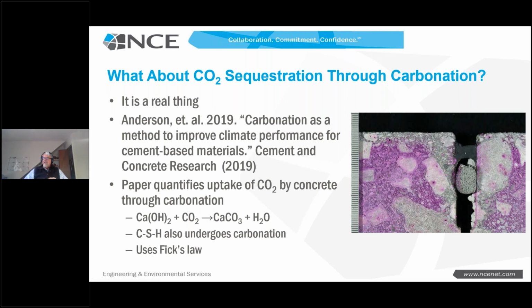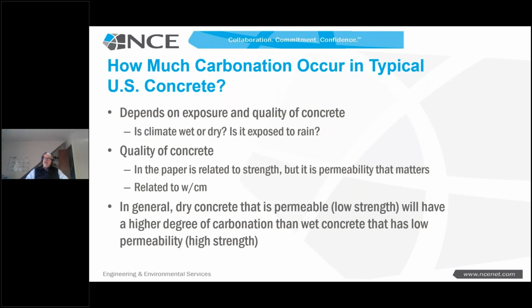And so this paper by Anderson et al., it's a great paper. It does talk about how CO2 uptake occurs, how we're converting the calcium hydroxide and CO2 to calcium carbonate, and it uses Fick's law, the assumption in the paper, and depends on the exposure and quality of concrete. And so if you are in a dry environment or an area that has periods of a lot of dryness, so maybe between monsoons, for example, and you have concrete that's fairly porous, you will see a very, very high degree of carbonation. And so a roof tile in a place like Africa, or possibly other places in the world, is going to really go through a high level of carbonation.